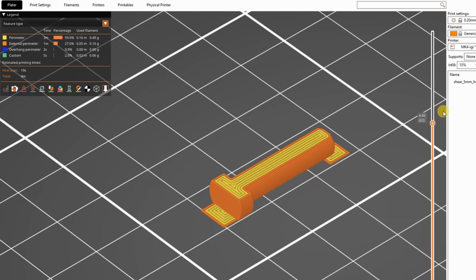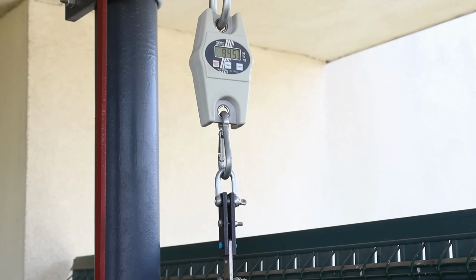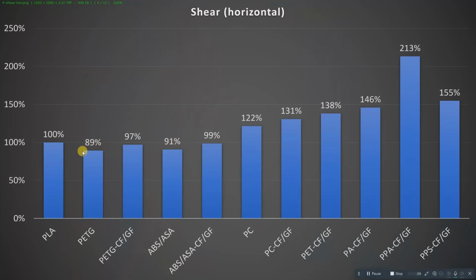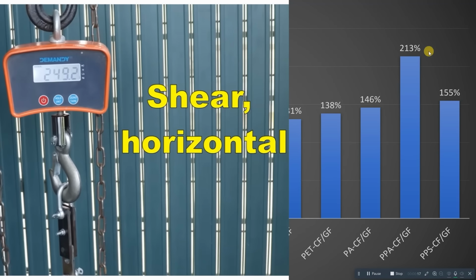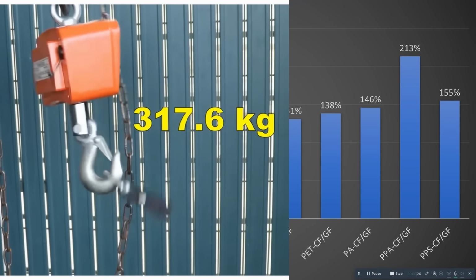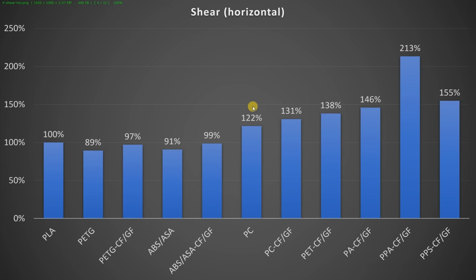Two-sided shear test. The object is printed in horizontal position, diameter is 5 mm, and I'm pulling until the break. From basic materials, the PLA is the strongest, but there is no big difference between them. Engineering filaments are stronger, but by far the strongest is the PPA-CF. And we can see that in every case, the fiber reinforcement helps with the horizontal printed objects.